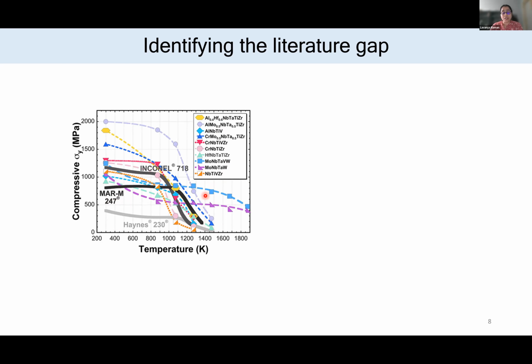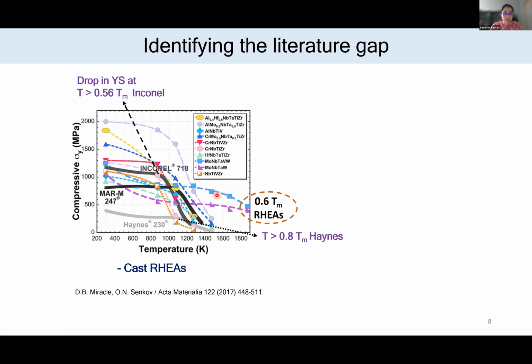Whereas these refractory alloys show a kind of steady state region where the strength is retained. But when we look closely, in both the cases, the strength drop happens at around 0.6 of Tm. The only advantage we have in these refractory alloys is that their melting temperature is very high. Because of that, we will have access to those high temperature domains which we cannot achieve using these superalloys. Only because of the melting point of these refractory HEAs can we go to temperatures above, let's say, 1300 Kelvin.